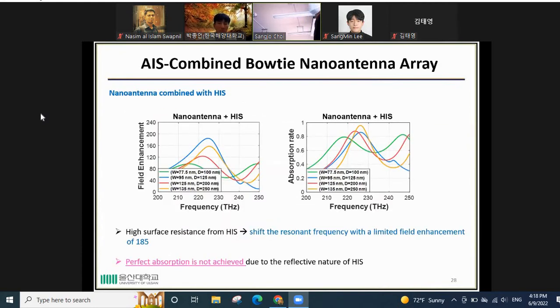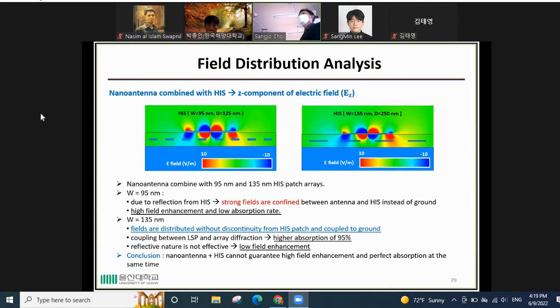Nano antenna combined with HIS for the field enhancement and also absorption rate. From this plot, we can see that HIS shifts the resonance frequency with a limited field enhancement of 185 because of the high surface resistance of the HIS. Also, from the right figure, we can see that perfect absorption is not achieved because of the reflective nature of the HIS.